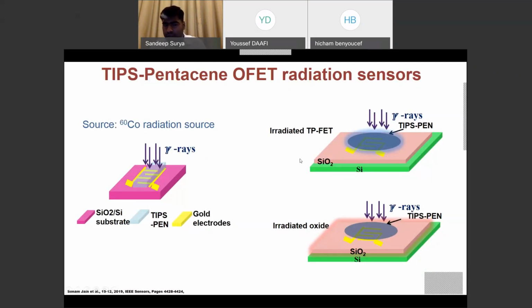Here we have taken two approaches. One, without irradiating any silicon dioxide, we deposited the TIPS-Pentacene, and then we exposed the gamma rays on top of the TIPS-Pentacene material. And the second case being, before even putting any TIPS-Pentacene, we irradiated the silicon dioxide, and then on top of which we deposited TIPS-Pentacene. These are the two different approaches that we took in this particular study to see the changes.